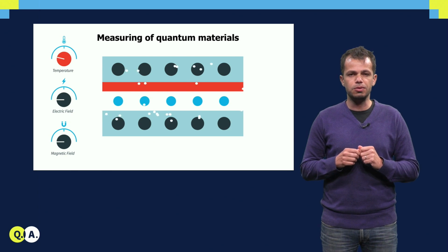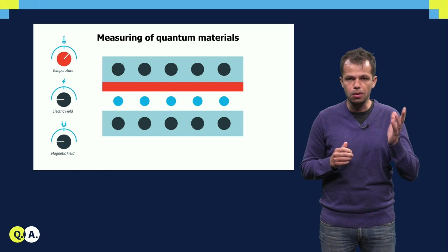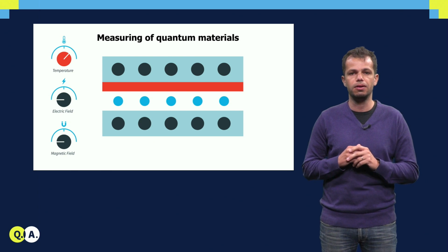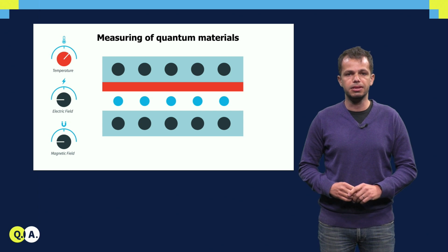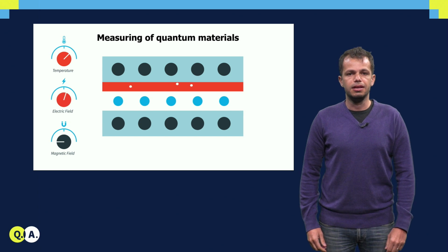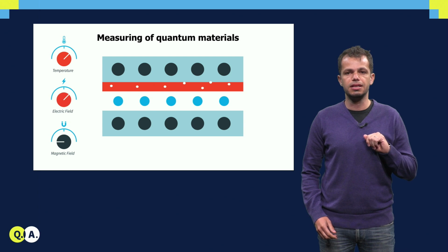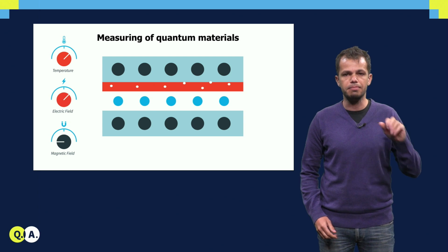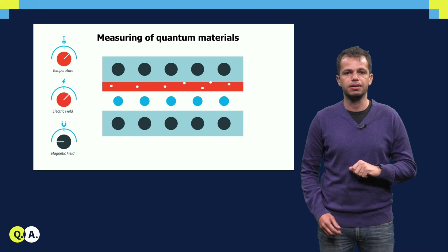If we cool it down to very low temperatures at which qubits usually operate, say below 1 degree above absolute zero, it would be insulating. However, we can make the material conducting by imposing a vertical electric field. The electric field forms a metallic channel at the interface between silicon and silicon germanium, which is then populated by electrons. The higher the electric field, the more electrons in the channel.